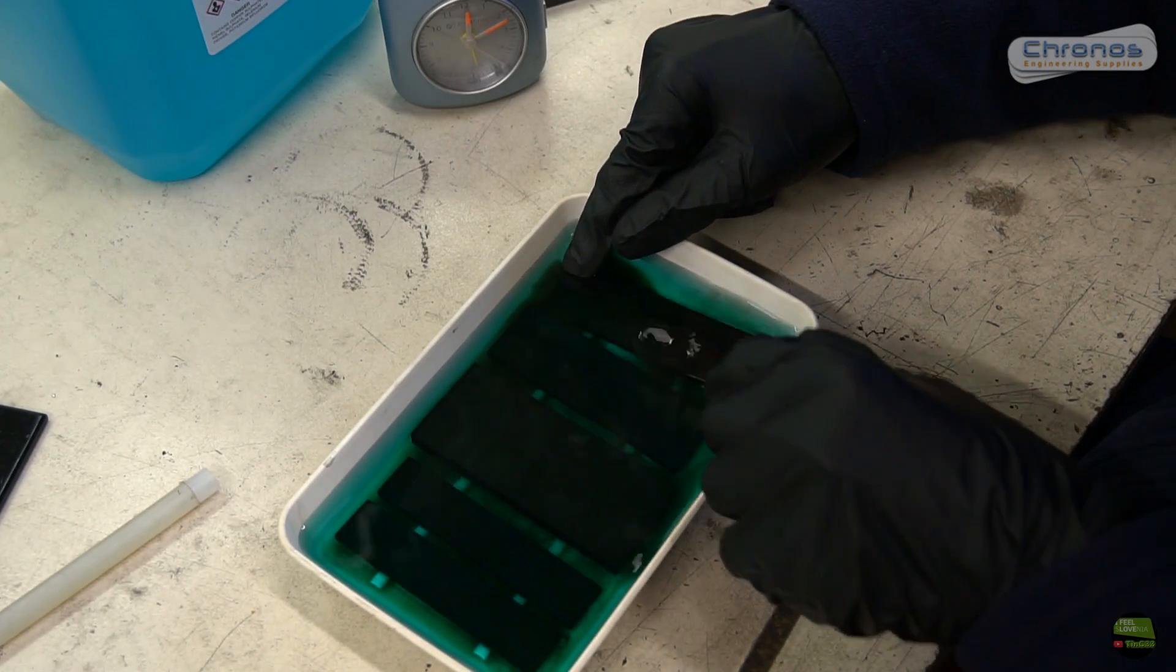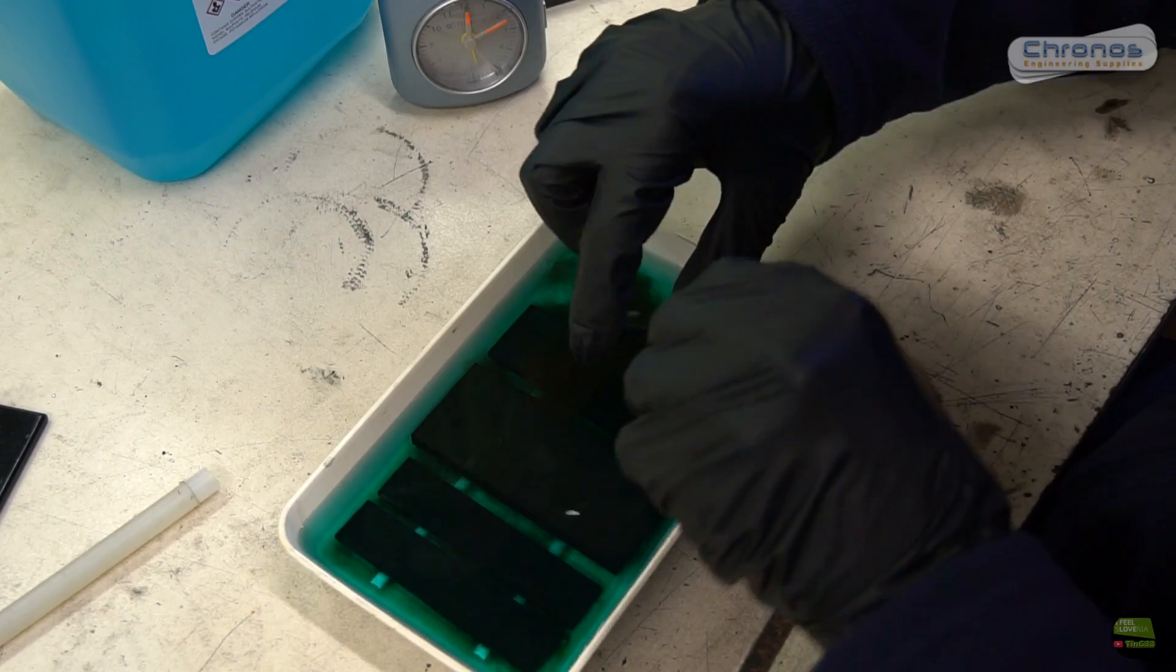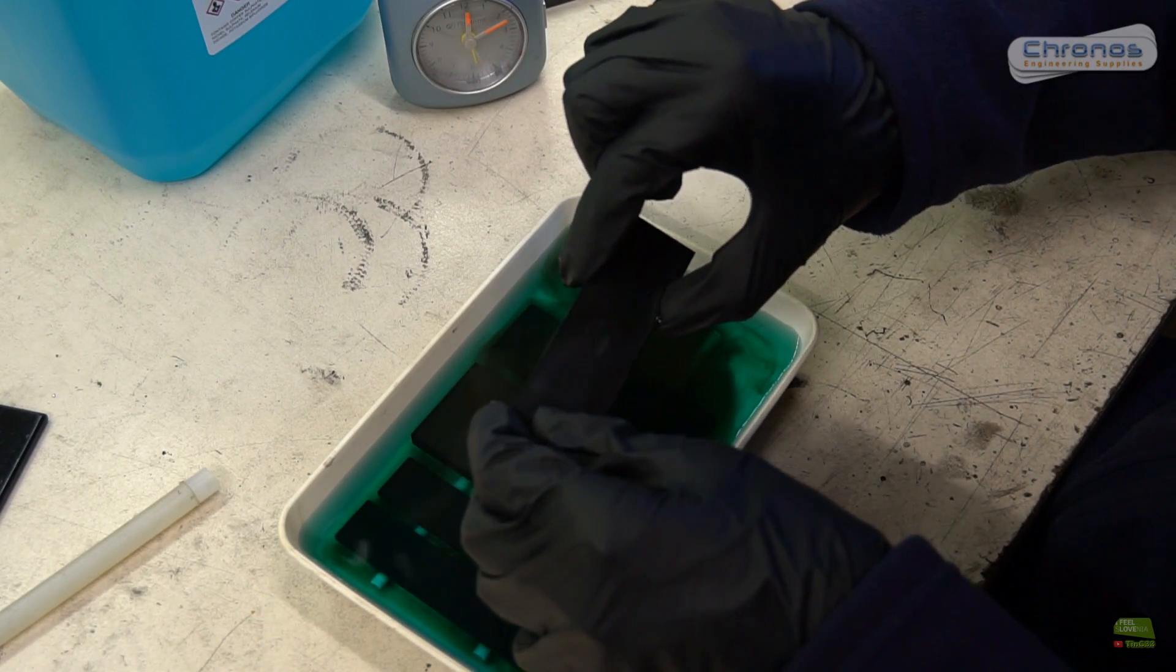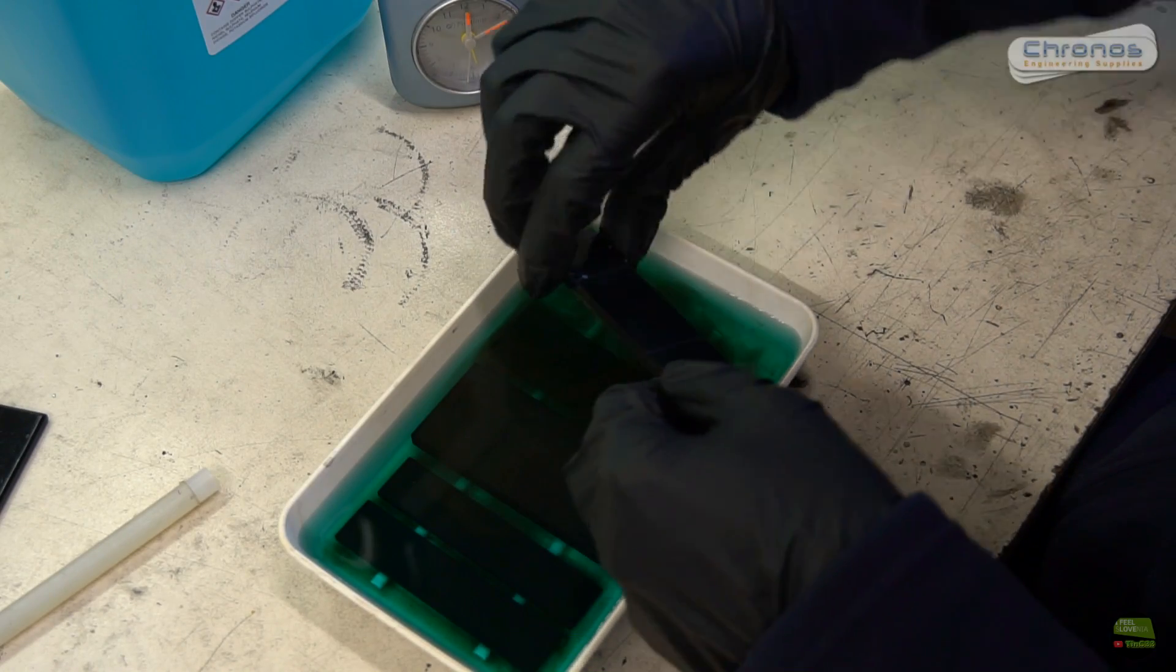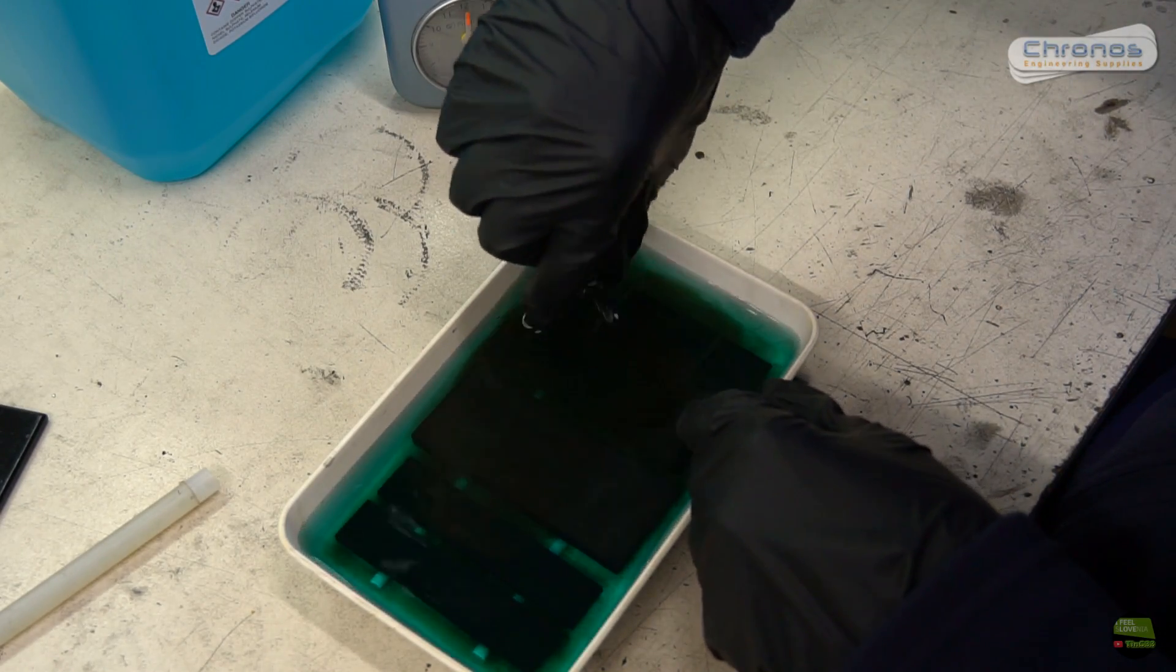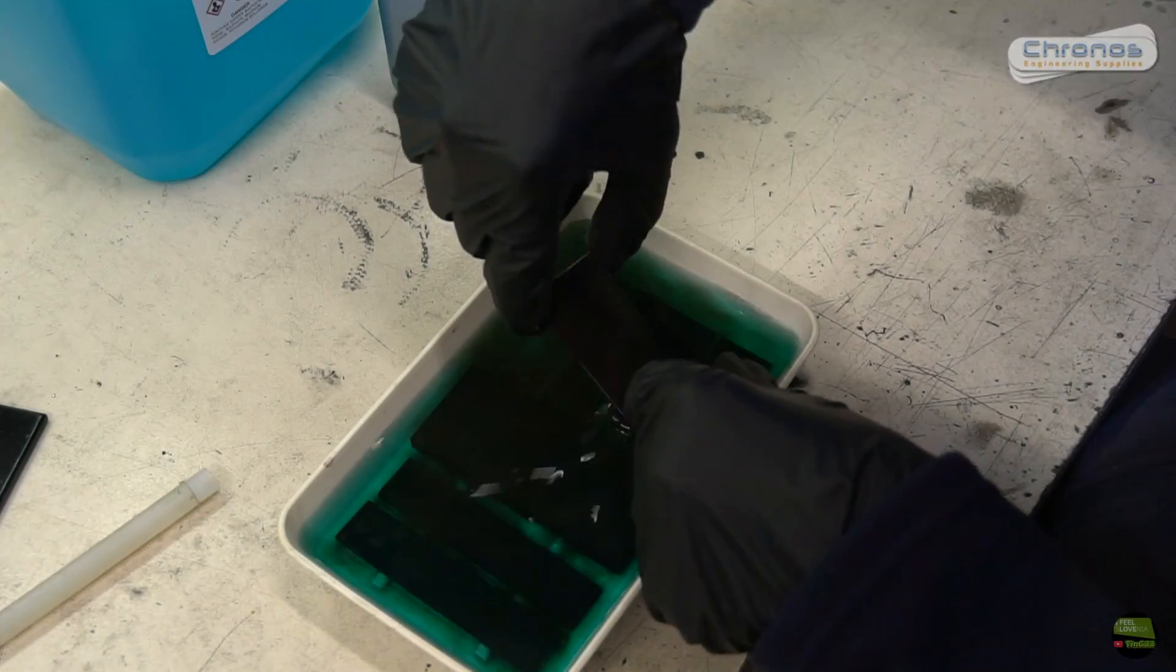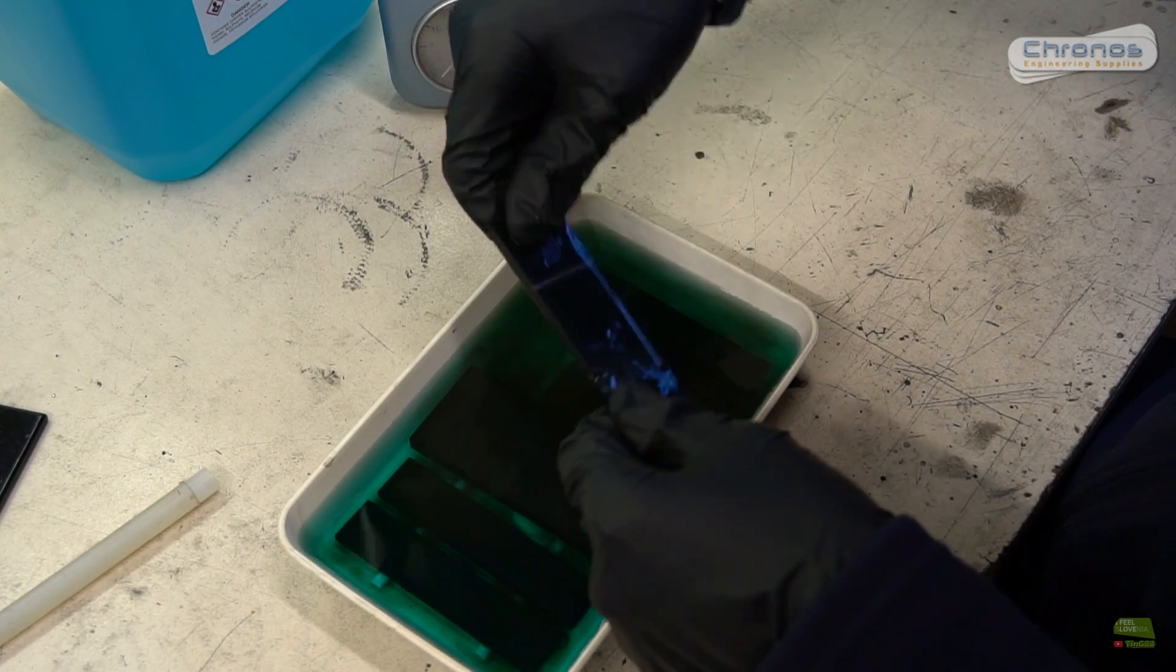After 10 minutes the pieces become black. And we can see also the solution becomes darker. I wanted to lift pieces from container bottom, so I used two plastic sticks underneath. But that was a mistake. Traces are much more visible like if we drop pieces direct to bottom. So I turn the pieces around and leave them for 10 more minutes.